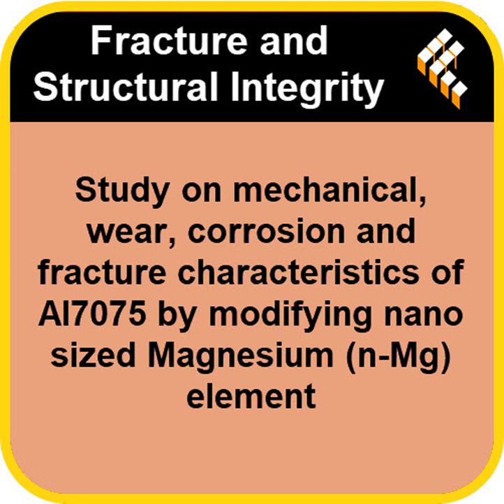Significant, but what physically changed inside the metal to achieve that much stronger resistance to failure? That 9.21% is caused by a kind of chemical marriage between the aluminum and the magnesium. You get the formation of the Al3Mg2 intermetallic compound. Okay. This compound is evenly dispersed, and it's these specific particles that act as the physical barrier to dislocation motion. They're just rigid, so they require far more energy to break or deform the material. And this is where that engineering sweet spot emerged. The greatest strengthening effect, a peak tensile strength of 152 megapascals, was seen at 2 weight% of nanomagnesium.